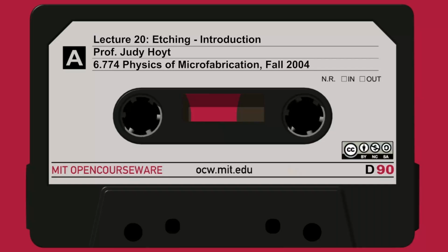Loading effects. There are things called macroscopic loading effects. And this is because you can deplete the etchant species across the wafer or across the whole etcher if you're doing more than one wafer at a time. So you'll see this. You'll put one wafer in, you measure the etch rate. Everything looks great. Now you put all 10 of your wafers in. All of a sudden the etch rate goes way down. So now you screwed up your etch. So in fact, when you measured the etch rates, you should have put 10 in, 10 dummies, because otherwise you can have this loading effect and you don't really measure the etch rate appropriately.